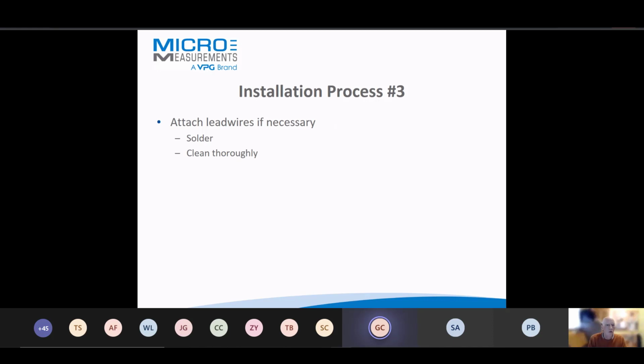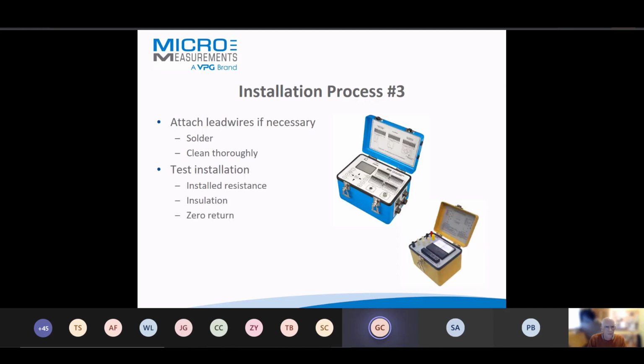If you use solder, you must clean the flux residue thoroughly, and you would then go on to test the installation. And these 3 basic tests are essential. We have installed resistance. Have you managed to damage the gauge, or have you mis-soldered it or shorted it out? We have the insulation resistance. The gauge should be isolated from the surface. And for these 2 tests, we use our little Model 1300 gauge insulation tester. These buttons here actually are in percentage deviation. Zero return, you can use a strain indicator, something like our P3 or other instrument, and that enables you to apply a small load and make sure the strain gauge returns to 0. This is assuming the structure they're bonded to returns to 0.